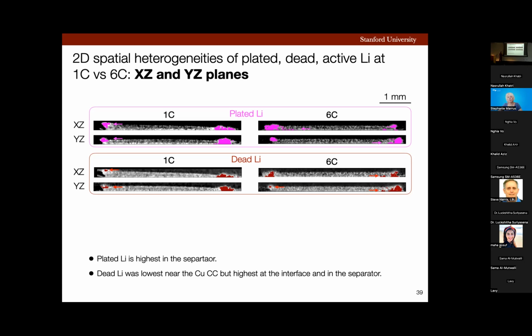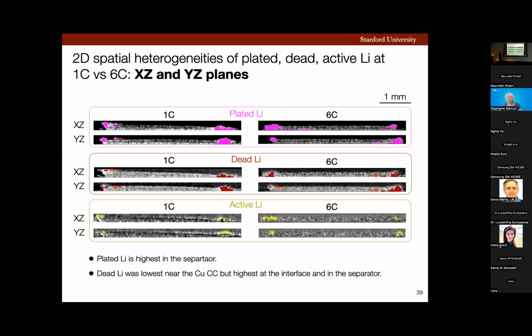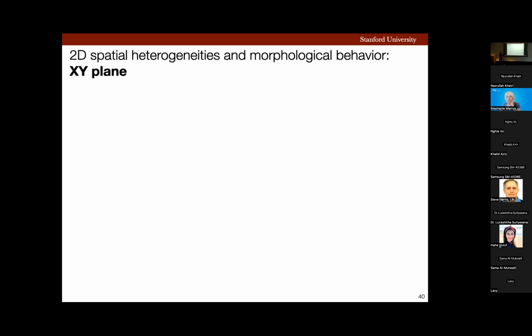Now, this finding relates to the finding of active lithium, where you can see these deposits are mostly near the current collector. However, in the separator, we don't see much active lithium, which means that lithium mostly becomes dead or irreversibly plated in the separator and in the interface, whereas lithium near the current collector has an electronic pathway open to it to find its way back in the battery. That's my hypothesis. Now let's correlate these cross-sectional images to the top view or XY images.